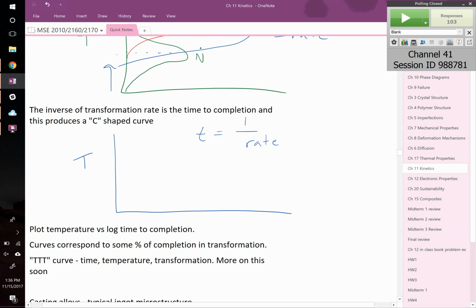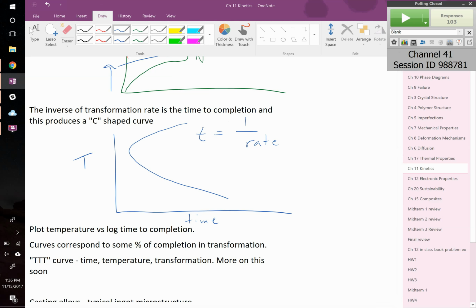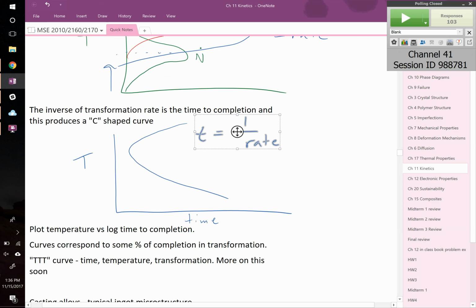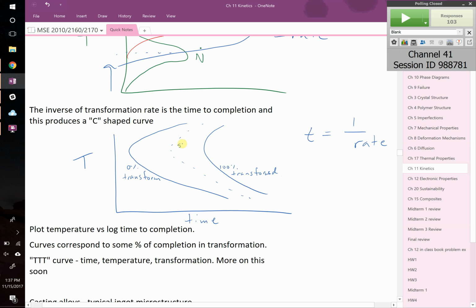You're going to plot temperature up here and time down here. And basically what you see is a series of what are called C curves. On the TTT diagram, you have a series of these C-shaped curves, and they'll normally draw them like this with solid lines and a dashed line. The solid line represents 0% transformed. This solid line over here represents 100% transformed. And this one would be 50%, right?